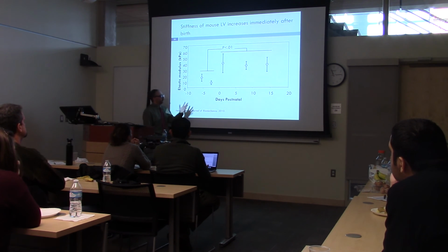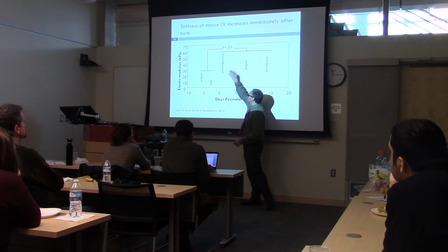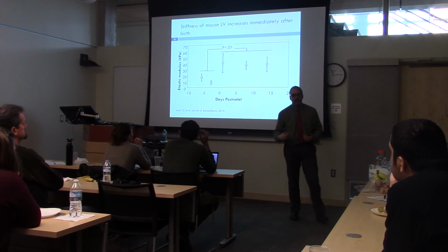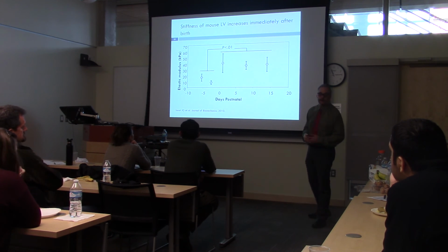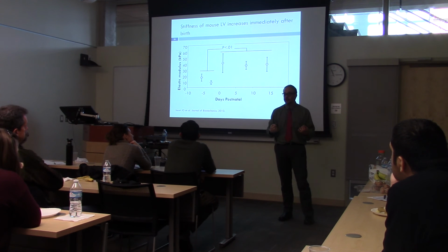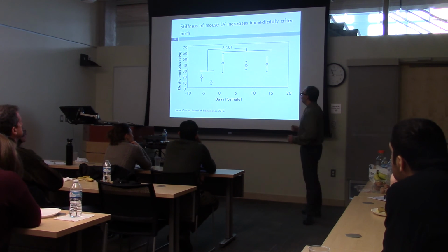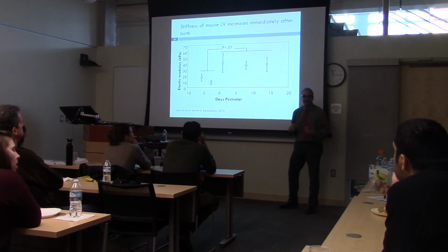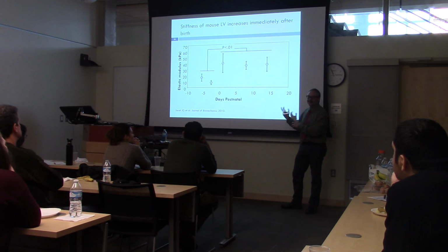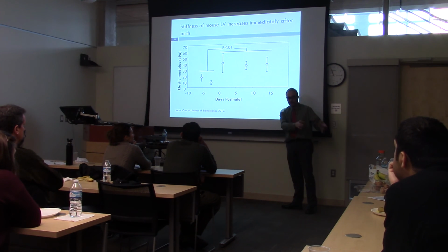Also, we were motivated by some studies that I've done looking at mouse development, where there is a big change in elastic modulus from an immediate synthesis of collagen that occurs right after birth in a mouse model. You can also do an infarct model, tying off one of the coronary arteries in a mouse and letting a scar develop, and you get a much bigger elastic modulus change in that scar area. So the mechanical properties are different as cells are maturing in a mouse model at least, and different in areas after a heart attack or an infarct.